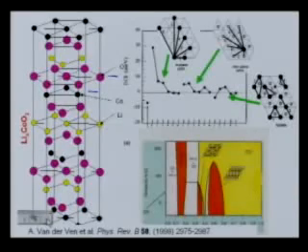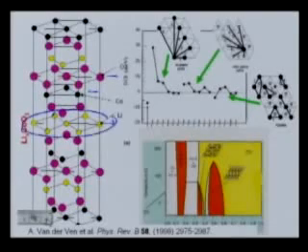Okay. Here's a lot more complicated system. This is the lithium cobalt oxide I showed you in the beginning. There's cobalt layers, there's oxygen layers, but the key component is the lithium layer. As you take lithium out, you have a lithium vacancy problem. So again, you expand in variables that only describe the occupation on this layer. So you don't really have to deal with the cobalt, with the oxygen. You just deal with that when you do the energy calculations. And you get a bunch of effective interactions.